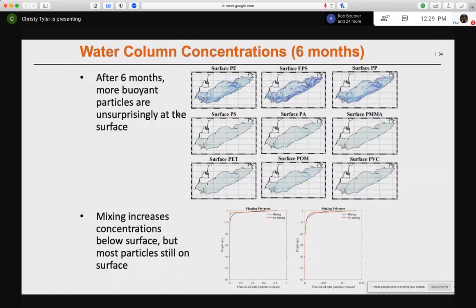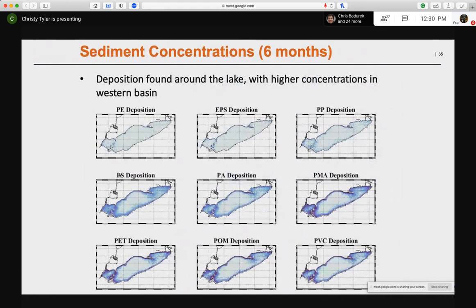So they ran the model for about 6 months, and then in the water column, they found, which is not surprising, that these 3 that are positively buoyant are mostly found in the surface waters, and that they do get mixed a little bit below the surface, depending on the turbulence in the area, but most of them are still up at the surface. Whereas with the denser plastics, for example, PVC is quite dense, that ends up on the bottom. And the concentration of these are kind of at the ends of the basin, especially this western basin in Lake Erie.